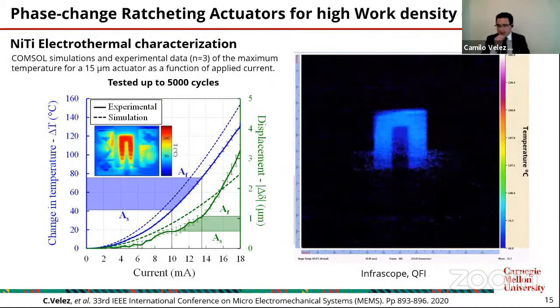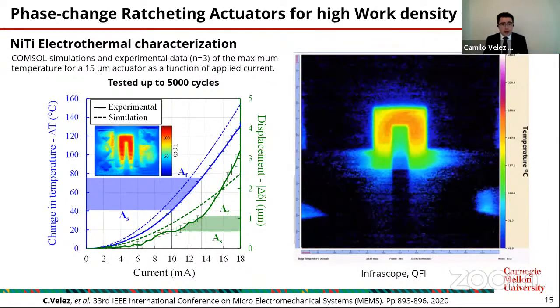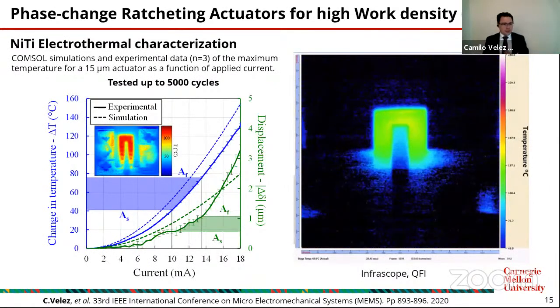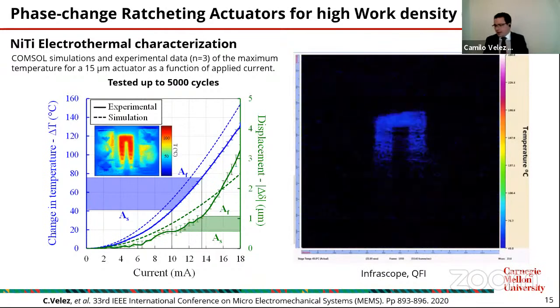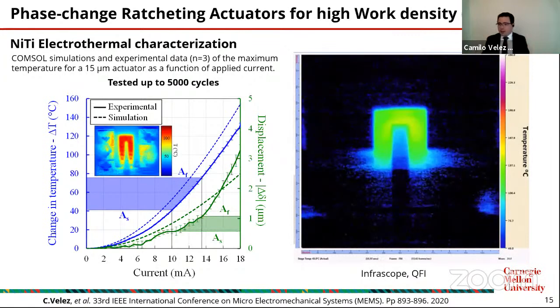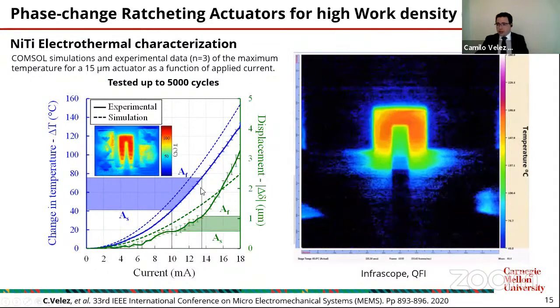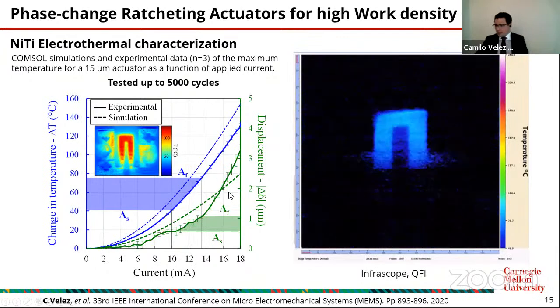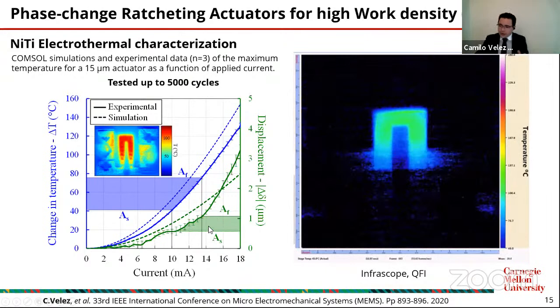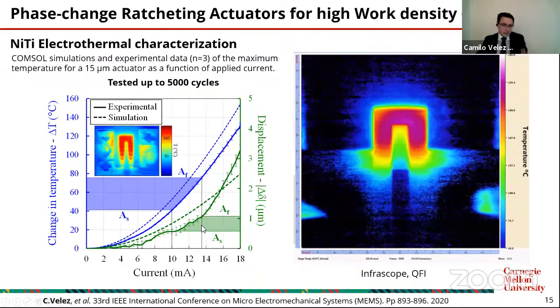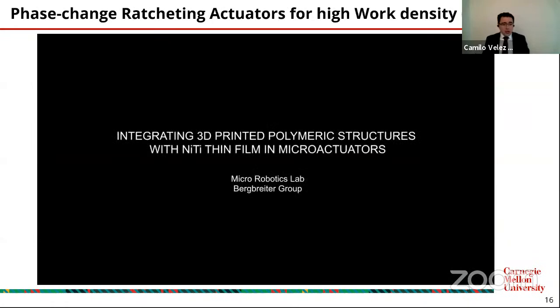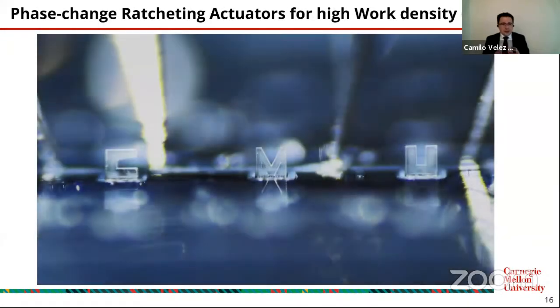We also characterized the change in temperature and the deflection, using a thermal camera, the Infrascope. When we pass current, we see how it heats up, and we compare with our simulation. This was the COMSOL simulation that we had here. Again, good agreement, but we are improving the technique, so we can always do a better job. But at the end, we managed to 3D print very complex patterns, like this one here.